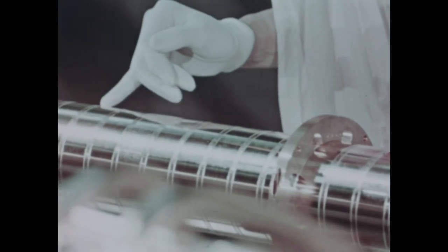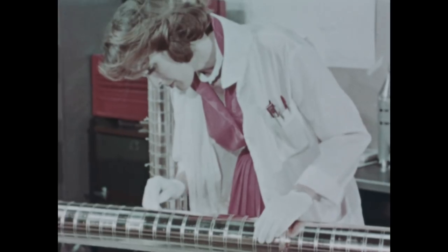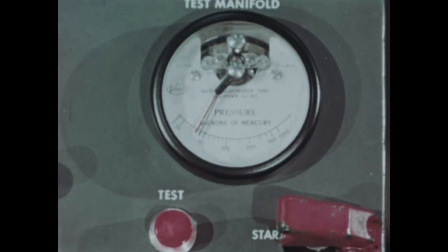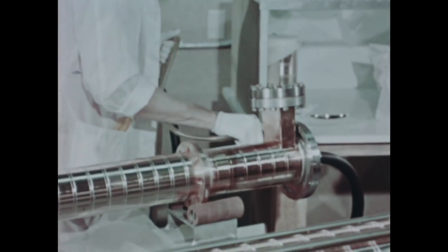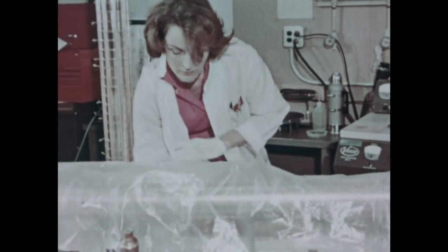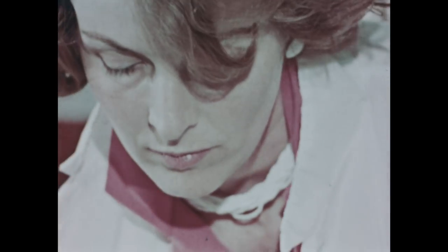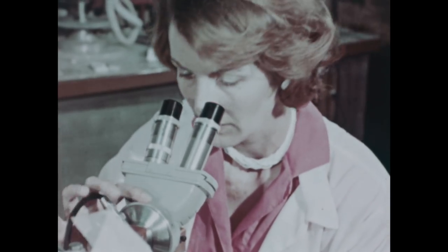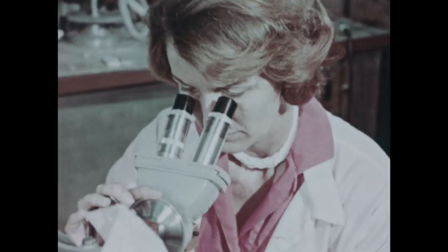Immediately after brazing, the sequence of the cylinders and discs is checked as well as the quality of the braze. The section is evacuated and leak checked by flowing helium first around the couplers, then under a plastic bag covering the section. If there is a leak, helium will enter the waveguide and be detected by a mass spectrometer. The section is borescoped. Each of the 86 cavities is visually checked for imperfections and cleanliness.